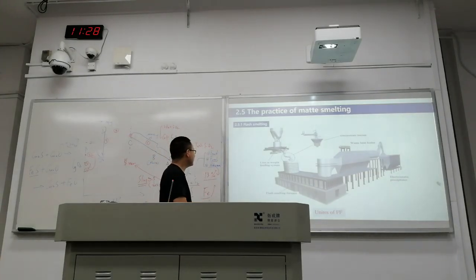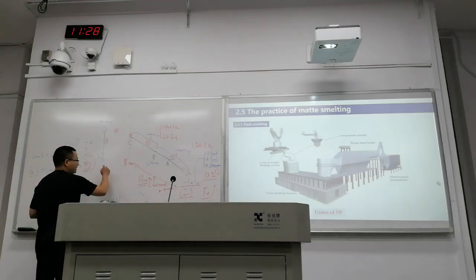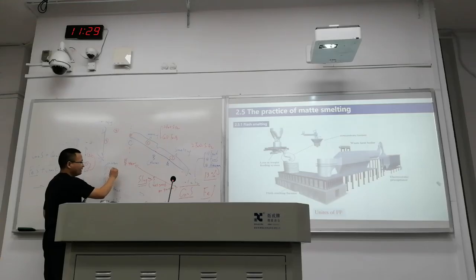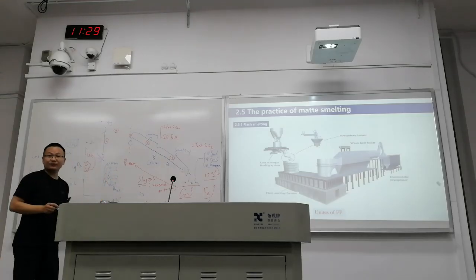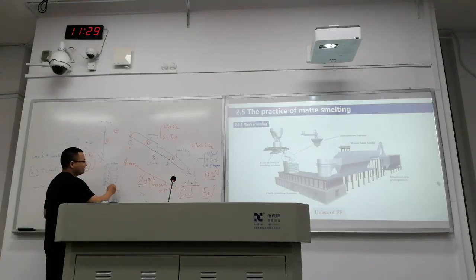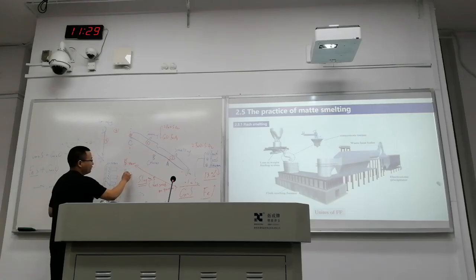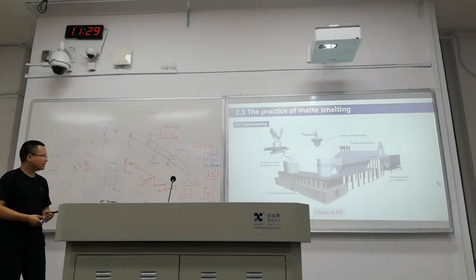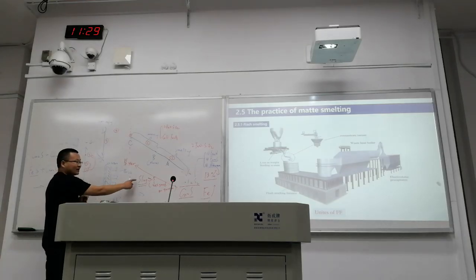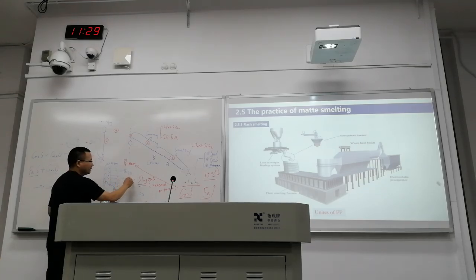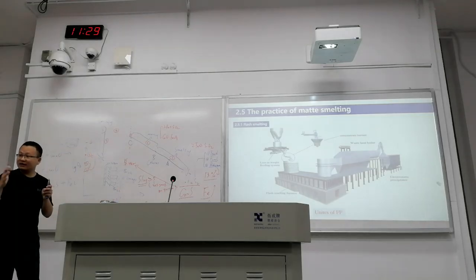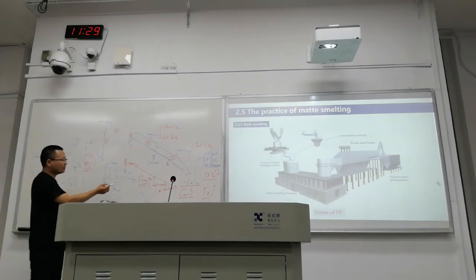And right after, if you are writing nicely over here, this is the frame. So we are going over the iron frame, and right after that, there will be brick. And after that, we are having some cooling element. And after that, we are having another brick. So several layers, and this is the layer which gets in contact with our slag, matte, or blister. And on the surface here, we will have linings of slag. The slag will be cooled down on the surface and make a new layer. So the slag will not contact with the bricks.